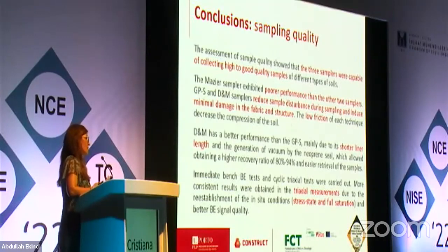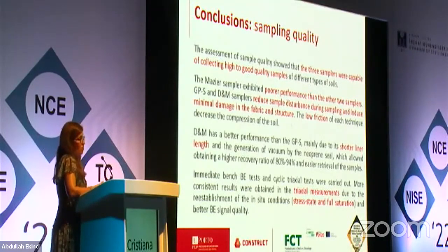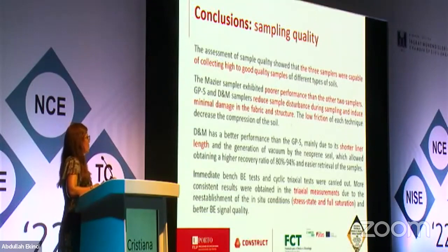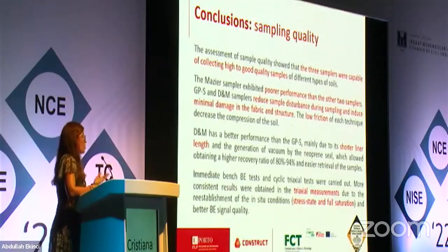So even though it's nice to have shear wave velocity data immediately after sampling, it is much more relevant to run the test even if it has some time effects, in order to reestablish the stress state and to have the soil fully saturated as it is expected to be in the field, in order to have more reliable measurements.